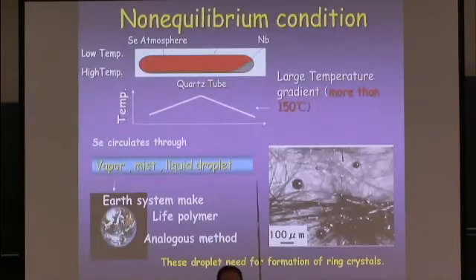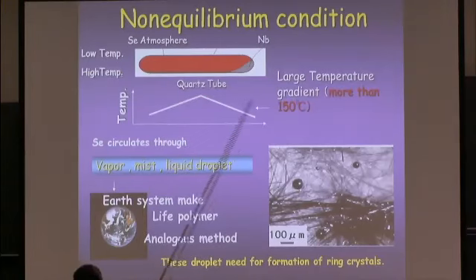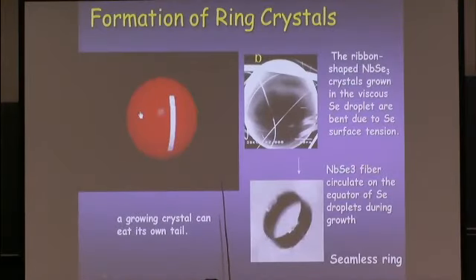In order to obtain the topological crystals, we need non-equilibrium conditions. There are large temperature gradients in the horizontal and vertical directions. So selenium circulates through the furnace as vapor, mist, and liquid droplets, like the Earth system. The Earth system makes life polymers. It's an analogous method. The droplet is here. This droplet is needed for the formation of ring crystals. The formation mechanism is shown in the video.